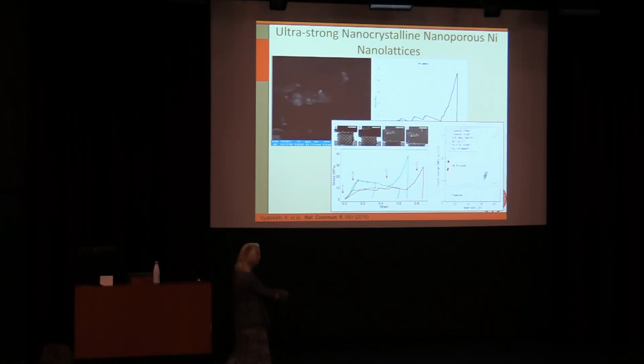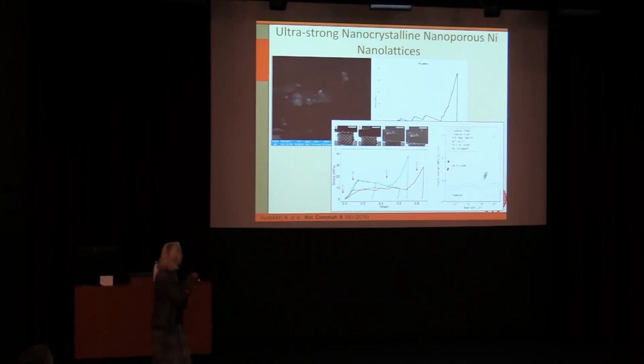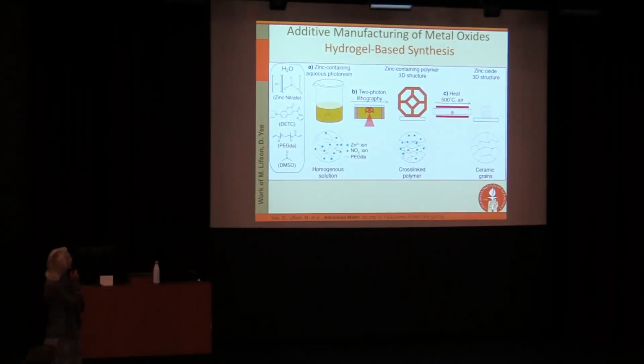And what we're learning is that, with this, we have to put in a huge break in the scale here, because for the nickel we made in this work, this is 100 microns and we're at 500 nanometers, so 3 orders of magnitude reduction in size, and this is where our strength is. So our strength is comparable to something that's about 100 microns to 100 millimeters in other metals. So it turns out that our materials are actually quite robust against defects, and so nanoscale is good.